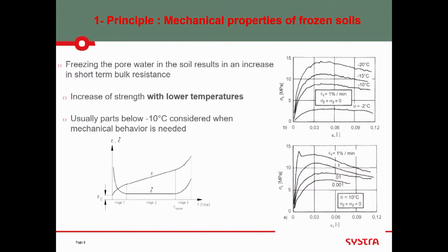In fact, as you can see, UCS is 2 MPa. If you use the same sample at -10, it's 8 MPa. At -15, 11, at -20, 13. So first of all, the lower the temperature, the higher the UCS, the unconfined compressive strength.